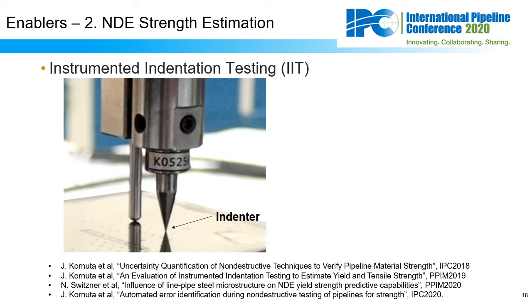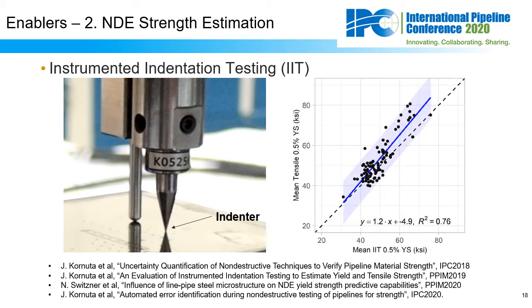PG&E has validated an NDE strength test called instrumented indentation testing, which uses precise, iterative load versus depth measurements to estimate yield and tensile strength. IIT has been validated using comparisons with laboratory tensile tests to adequately produce an estimate for yield strength. And some of the PG&E documentation can be found in the publications shown at the bottom of this slide. So if you'd like to take a look at some of these publications, please email the address you'll find in the last slide.